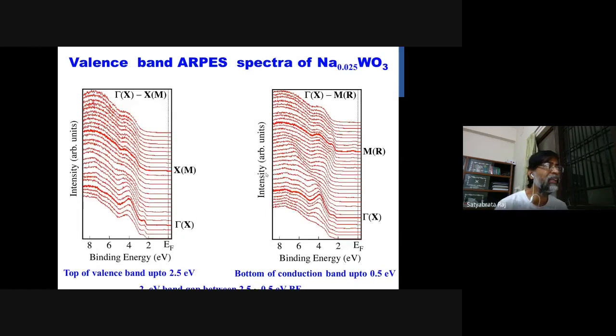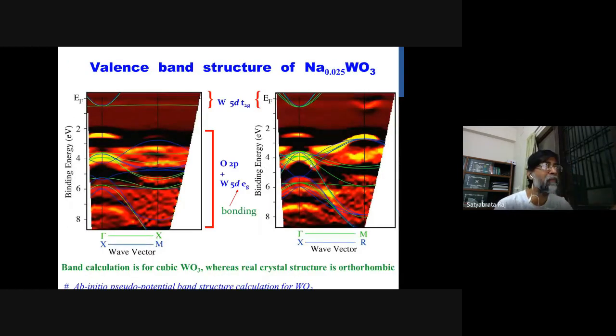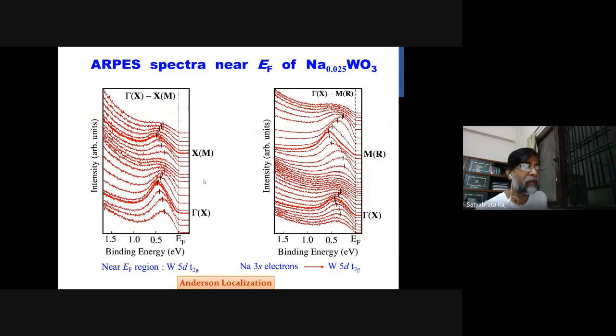So this is the valence band, and this is the measurement of the valence band mapping, and you can see clearly you have a Fermi surface appearing at the M point, and also a new band is appearing around 2.5 eV, which is not predicted in the band calculation. This is very worrisome, that why it is appearing. So to understand these things, we have measured the low energy spectra near EF, which only shows a 5D character of the tungsten, but this band is never crossing the EF, making it insulating.